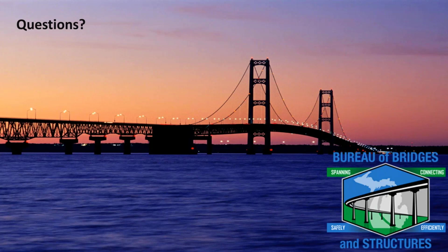Okay. Did you have concerns about the permeability of the concrete and freeze-thaw cycles of moisture within the concrete members under the ramps? Want to address that one, Steve? Yeah. Typically, if you're going to do flexural repair on a beam, you'll space out the FRP wraps to a 1-inch gap or so to allow for moisture exfiltration. But as for column confinement, what you're also doing is effectively creating a moisture barrier as well. So long-term studies have shown that that's not an issue.